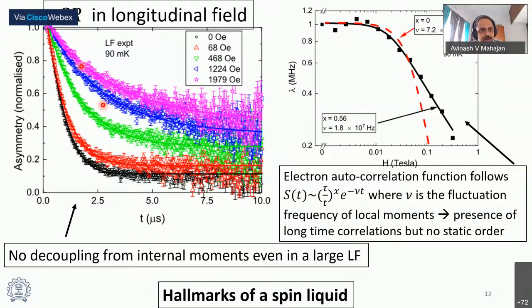The other point is, when you now try to fit this, you find that this depolarization is happening because of electron dynamics, electron moment dynamics. So if you normally just assume that the electron autocorrelation varies just exponentially as e to the minus nu t, where nu is just the fluctuation frequency of local moments, then it doesn't fit the data well. Okay, one needs to take another tau by t to the power x in the electron autocorrelation function in order to fit these lambda as a function of magnetic field, the magnetic field variation of the electron relaxation. And this is again considered an evidence of temporal correlations being present even when there is no static order. Okay, so both these are hallmarks of quantum spin liquid.